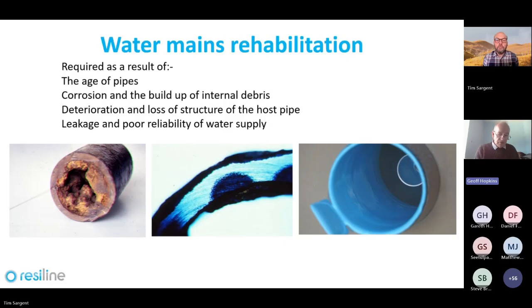I think the point to stress is that the pipe condition varies from virtually as good as new to completely shot, and there is a complete spectrum of condition and serviceability in the existing networks. So spray lining is not a universal solution for all pipe issues, but it's a tool in the box that can extend the working life of a large percentage of pipes for in excess of 50 years. So next slide, please, Tim.